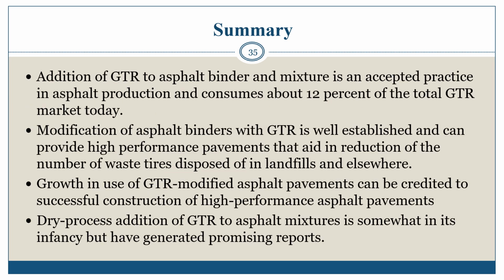As an accepted practice of asphalt production, GTR modified asphalt binder and GTR modified asphalt mixture consumes about 12% of the total GTR segment of the recycled tire rubber market. Asphalt modification with GTR is well established and can reduce the number of waste tires disposed of in landfills while providing high-performance pavements. Growth and use of GTR modified asphalt can be credited to construction of high-performance asphalt pavements. Dry process addition of GTR to asphalt mixtures, while it is in its infancy, has generated promising reports.